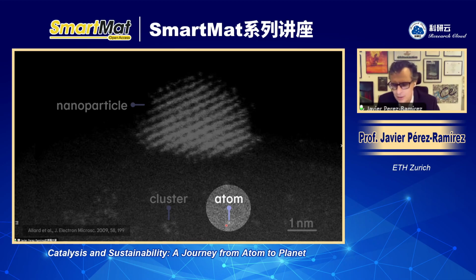And the reason for working with single atoms and exploiting single atoms is because they achieve, in a way, maximum dispersion. It's the best way to disperse metal because in a nanoparticle, as you know, only surface sites will be accessible by reactants. And so we are actually underutilizing quite a lot of the metal very often. So how can we make catalytic materials that only contain atoms? How can we use these atoms to carry out unique reactions with a unique reactivity in a sustainable manner?